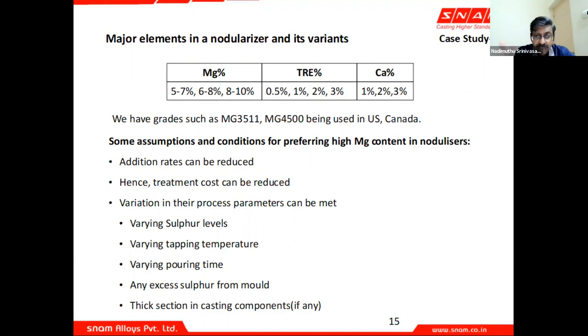Now, some of the assumptions that people have when they prefer high magnesium content in nodulizer, they feel that if I buy this, I'm going to reduce my treatment alloy percentage. True. But do you think the treatment cost can be reduced? Now, these are the areas that are contentious. Your addition rate alone you will reduce, but you end up with a host of problems that we will show as we go through this slide in this case study. The variation can be met for varying sulfur level by varying tapping temperature, varying pouring time, any excess sulfur from the mold, thick section in the casting.